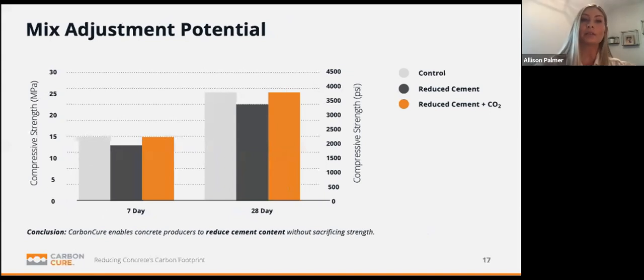The light bar on the left is our control. The middle bar is that same exact mix, but with a 5% cut in cement. As you would expect, when you take out that cement content, you're going to see a drop in strength. The orange bar all the way to the right is the same mix with 5% cut in cement, but with CO2 added back in. So it brought the mix back up to where it was, at about 4,000 PSI at 28 days. This is a really great example of an optimized mix.